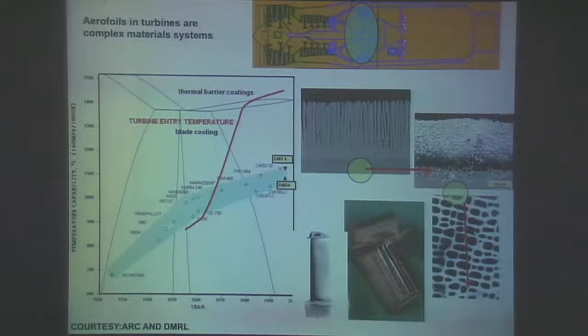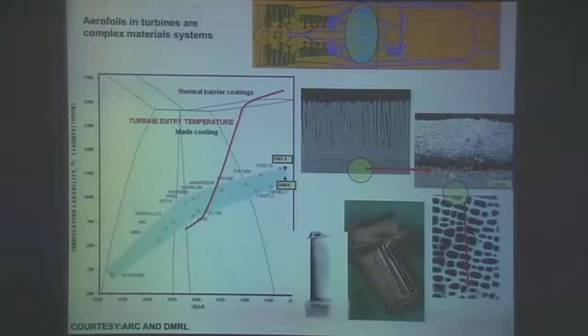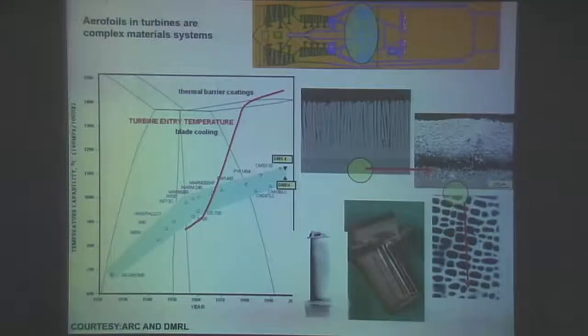is the actual temperature capability of the material has improved over the years through precipitation hardening and various processing technologies that I'll talk about to about 1100 degrees centigrade, which is also a very high fraction of the melting point. All of you metallurgists will understand the role of diffusion and so on as you approach the melting point. And therefore, this is an incredibly high fraction of the melting point for nickel-based superalloys. But also, an additional improvement in temperature capability comes from cooling, okay?